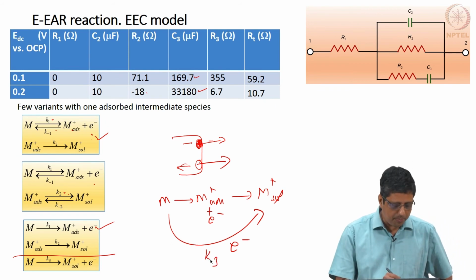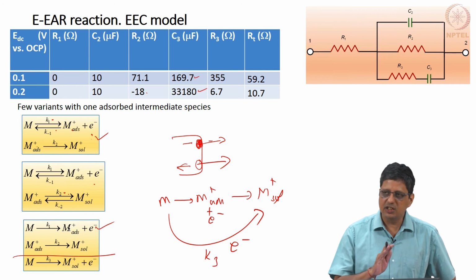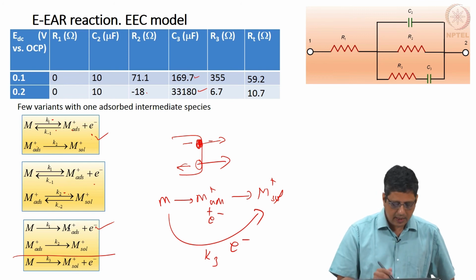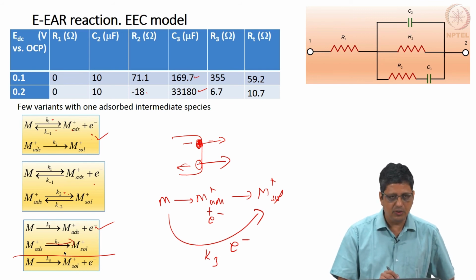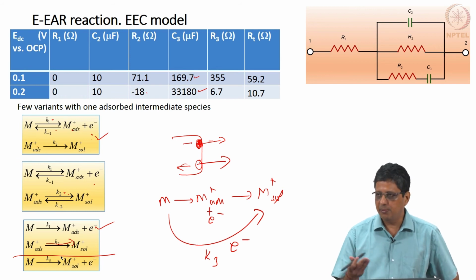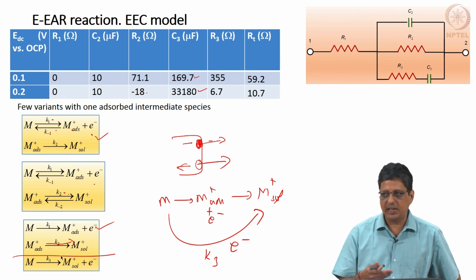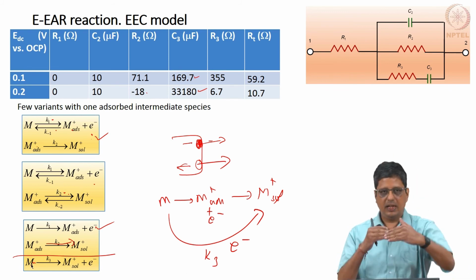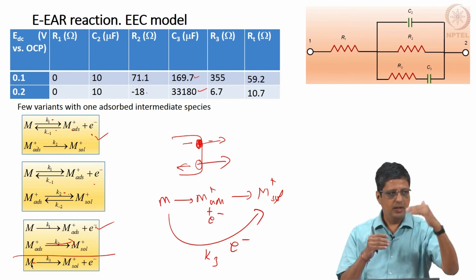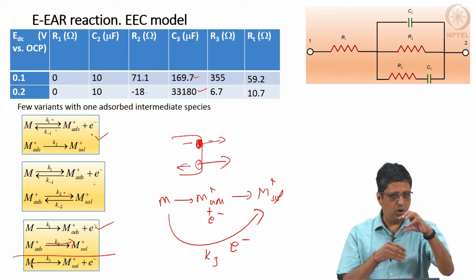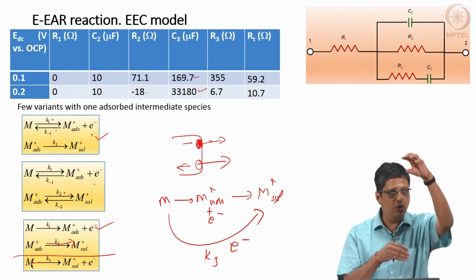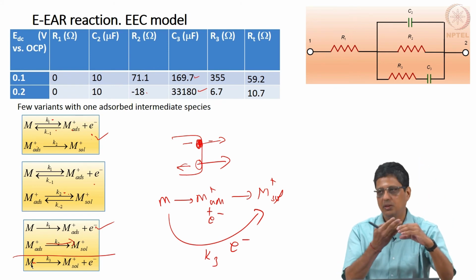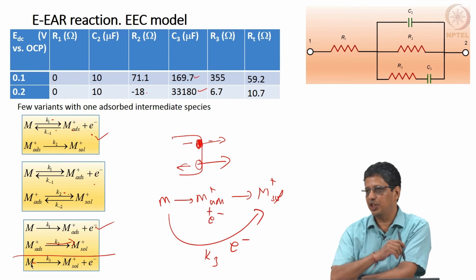Okay. So, if metal becomes metal adsorbed and the surface is mostly covered with metal adsorbed, then only this reaction will happen to a large extent, the third reaction will not happen to a large extent because there is no bare metal. Do you understand? This when it happens, it will regenerate the metal. A metal is there, it goes out, another metal below that is exposed. Whereas, if an electron is taken out, it does not go out. Until this goes out, the metal atom below that cannot lose another electron, that is the assumption here.